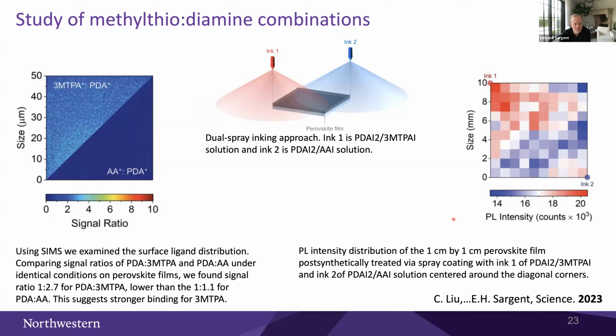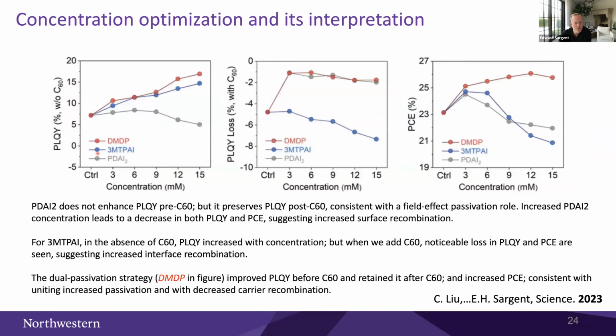bimolecular strategy. The concentration dependence is also quite interesting as a function of whether you take a single molecule class or whether you look at the combination of molecules. We can see that if we use PDA-I2 alone, we don't get the enhanced PL quantum yield before putting the C60 on, but we preserve what PL quantum yield we have when we do put the C60 on. So this is suggestive of the field effect passivation role.